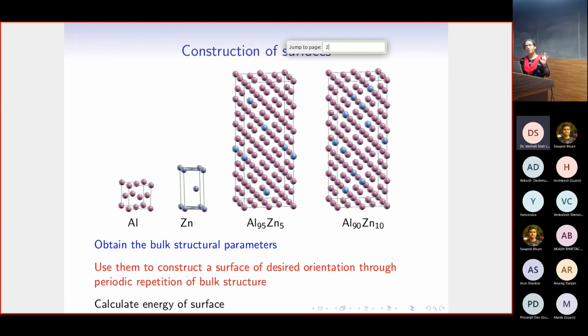And then once we have this surface of desired orientation, we should be able to obtain the surface energy. And similarly, these desired orientation surfaces we can put together and be able to get the interface energy. So what I have shown you here is the structure of aluminum, zinc, and two of the aluminum-rich zinc alloys that are of interest to our materials engineering team here, which was we have chosen the 95.5 AL95 zinc 5% doping and zinc 10% doping in this.